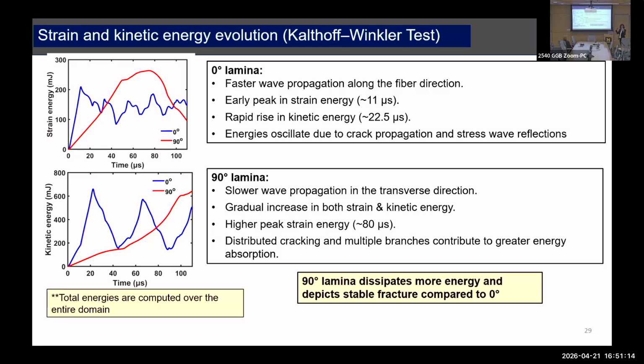And of course, as the wave propagation perpendicular to the fiber direction is slow compared to 0, the strain energy takes much longer to reach this speed. So everything basically falls to exactly the same conclusion that we are seeing in the crack propagation behavior. Overall, the conclusion is that the 90 degree lamina demonstrates more stable crack growth.